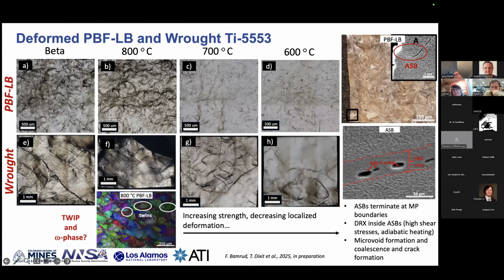This is a nice example up top here in the corner where we see an adiabatic shear band that terminates at a melt pool boundary. And this may be why we see these improved properties with additive. Also shown here is a nice example of dynamic recrystallization occurring inside of one of these adiabatic shear bands, and microvoid formation and coalescence, and ultimately crack formation.